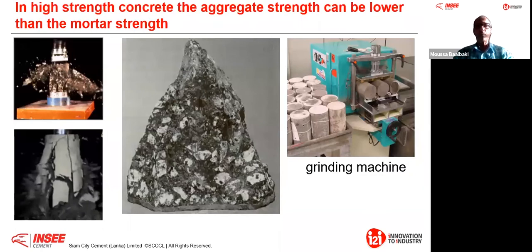If you take, for example, high strength concrete, and you go for tests like compressive strength, here you see that the failure happens through the coarse aggregate, and that is the main reason. If you come to I2I, we have a grinder. Therefore, in some tests for high strength, for example, where we use cylinders, we need to prepare the surface. We need to grind the surface to assure the parallelism and the perpendicularity. Otherwise, you have eccentricity when you test in compressive strength. That is the main reason that we have to adapt even the technique of testing. And this is because the aggregate could be in terms of strength lower than the cement hydrated product.